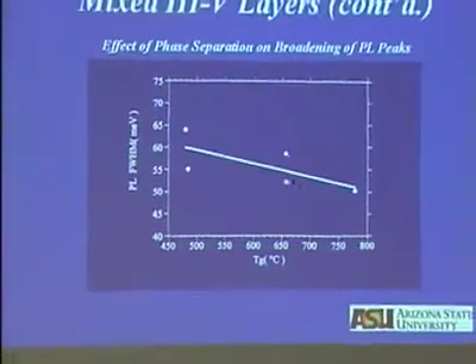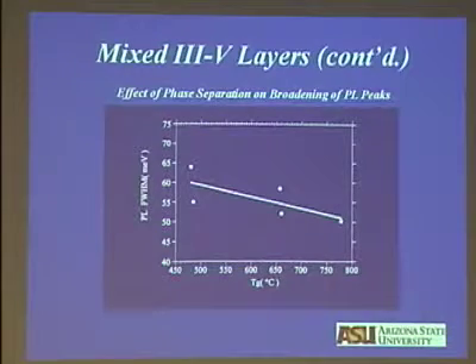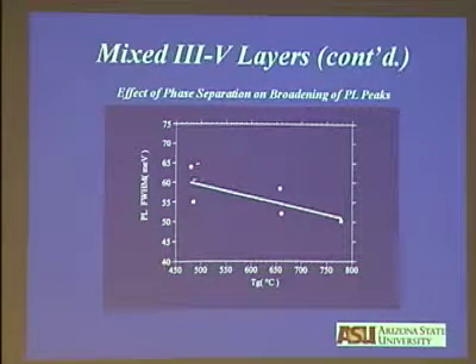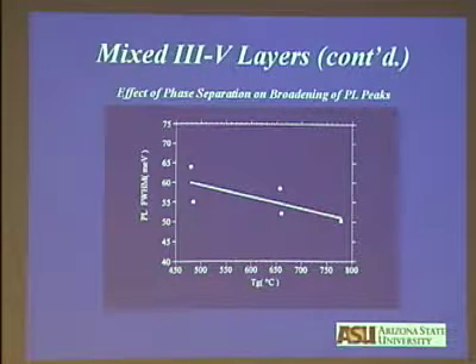Now, how does phase separation affect the width of the photoluminescence peak? That's what we did and is shown here, just the opposite. Now you have indium-rich regions and gallium-rich regions in indium gallium phosphide. Indium-rich regions have a lower band gap, and gallium-rich regions have a higher band gap. So when you measure photoluminescence, the peak width changes. The full width at half maximum changes depending on the growth temperature. And that's what we tried to show you here: when you are growing at high temperature, the difference in composition between the two regions is much smaller, so the width will be smaller, whereas when you grow at low temperature, the width is larger. So this whole picture is internally consistent: the occurrence of phase separation affects both optical properties and electronic properties of the layers.